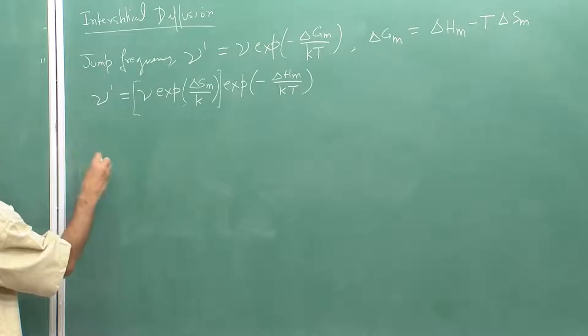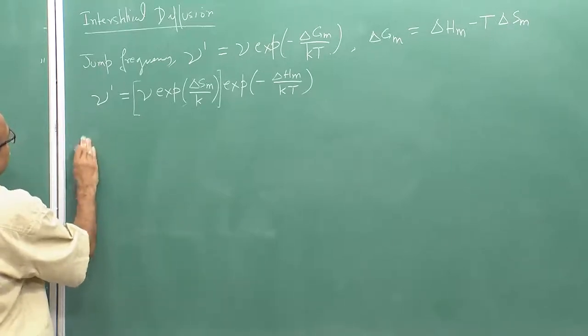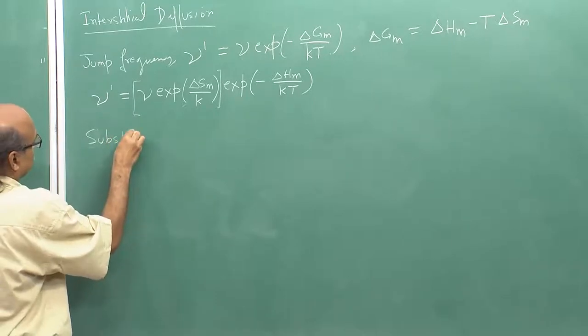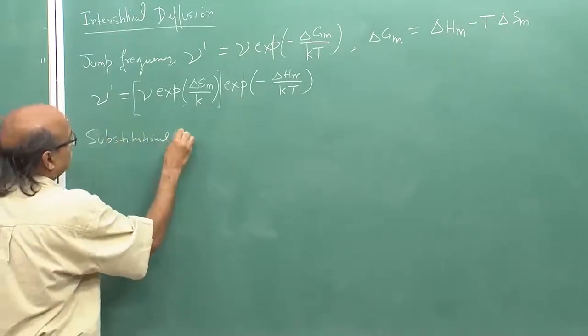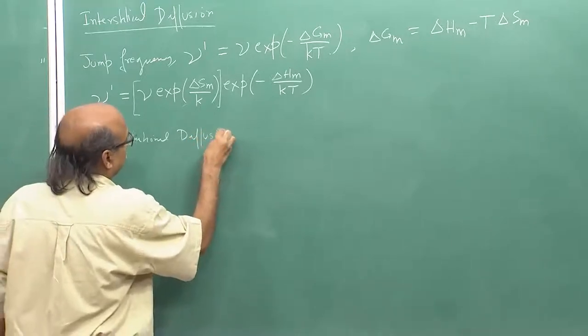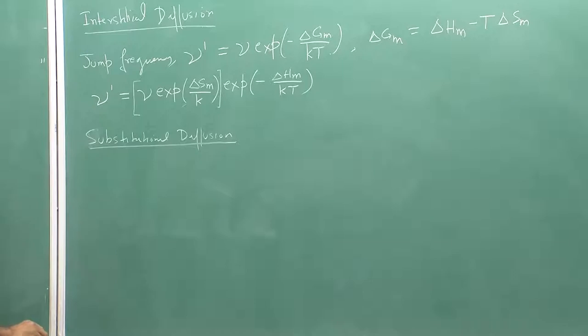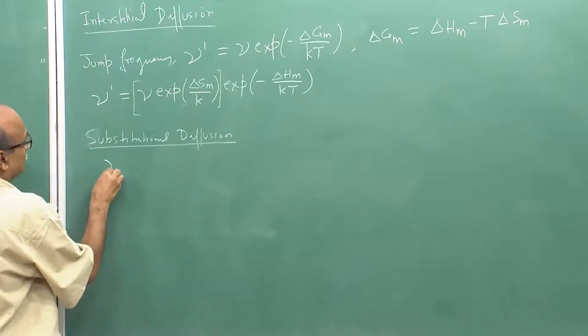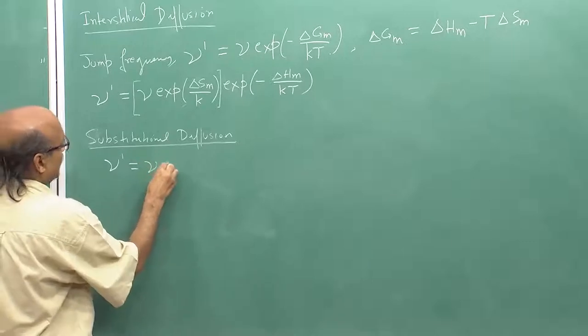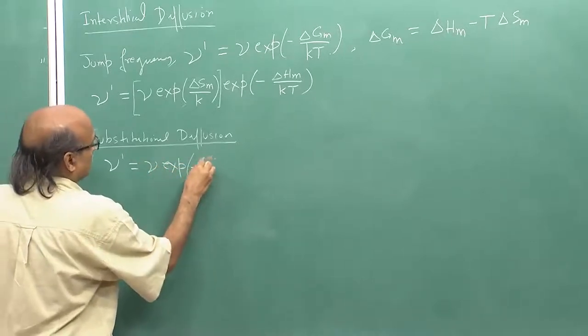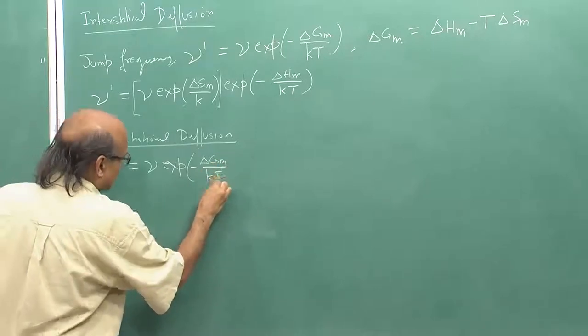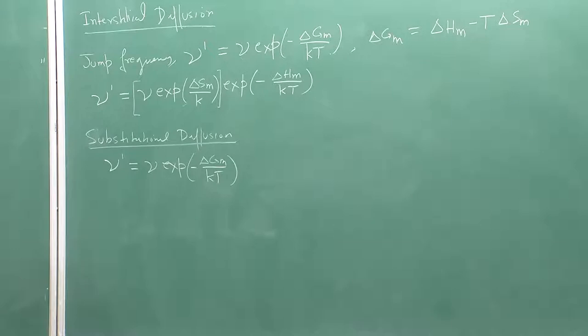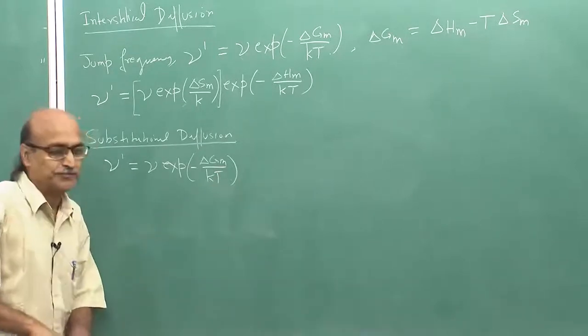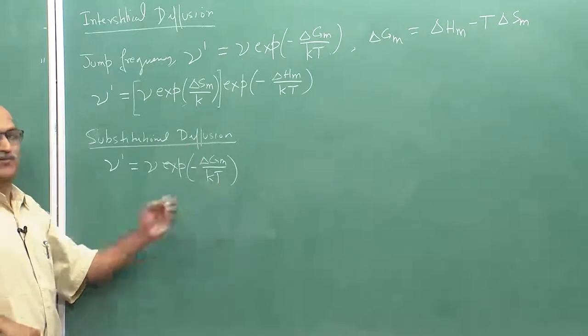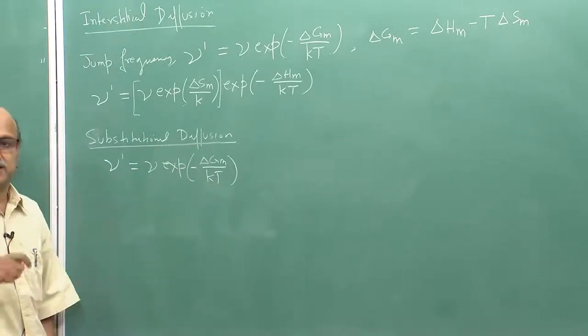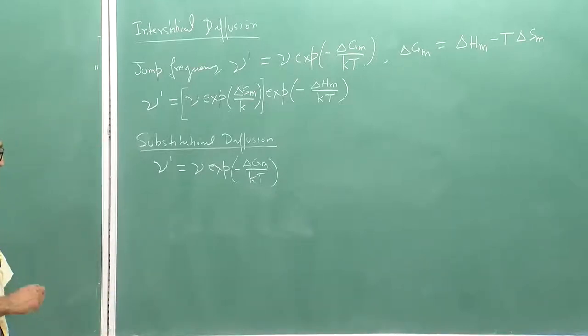Now, consider the substitutional diffusion case, where the vacancy mechanism is active. So, in the case of substitutional diffusion also, one can write nu prime to be equal to nu exponential minus delta Gm upon kT. These terms would still be there. However, there would be one more term that would have to be added to this expression, because for a jump to be successful, the neighboring site to which the jump is taking place has to be vacant.